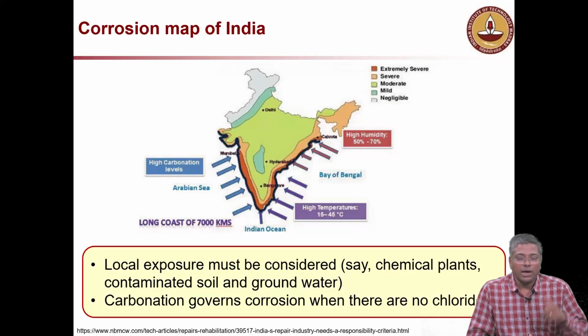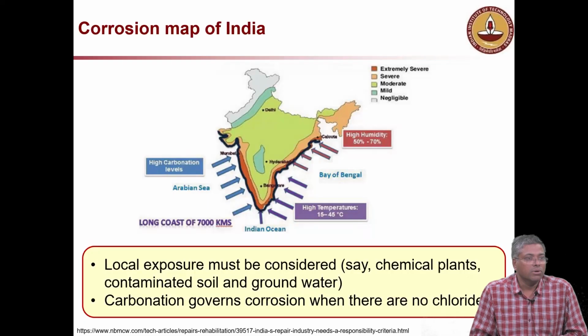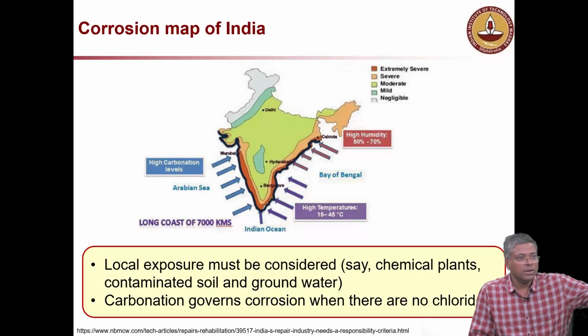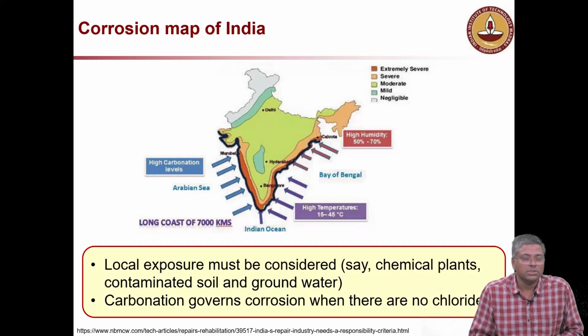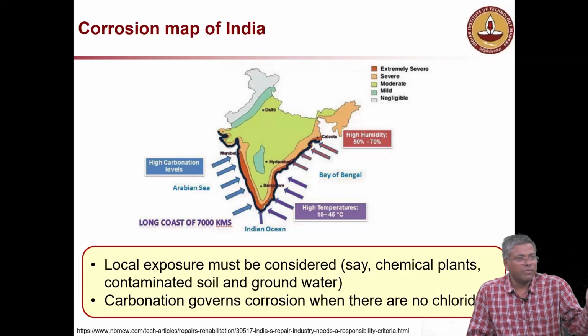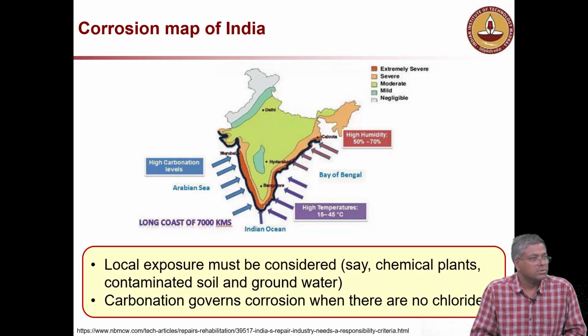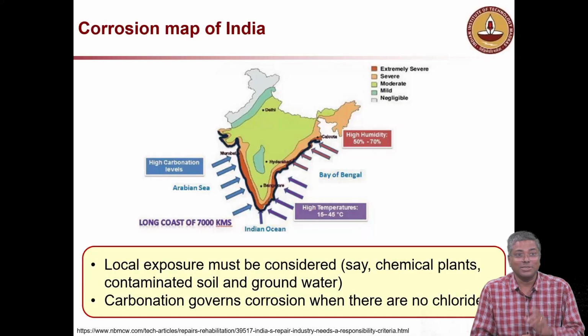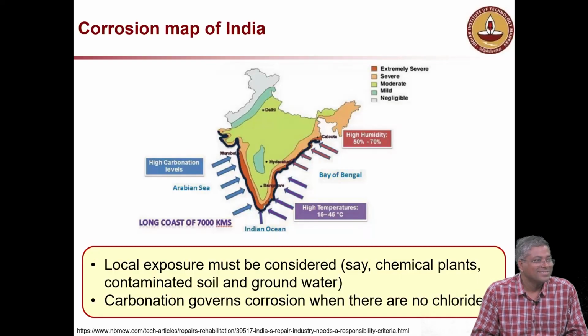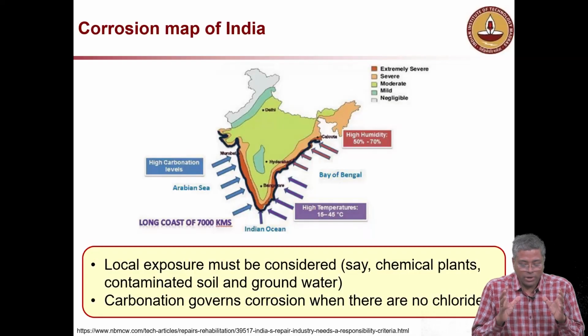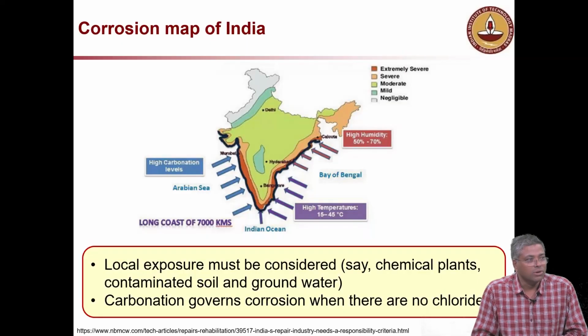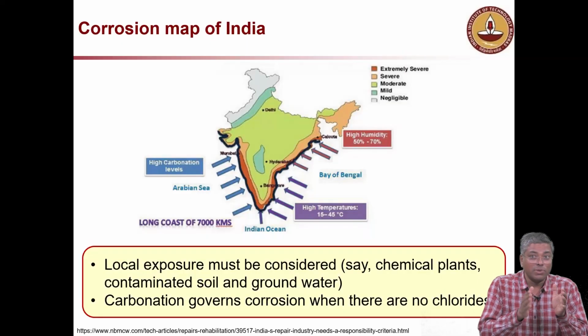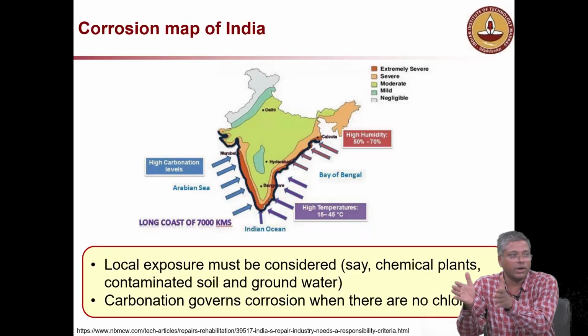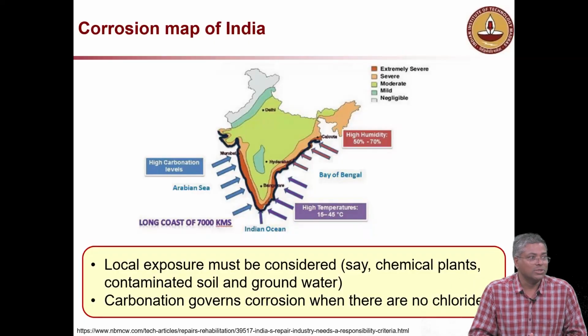Okay, I had an experience with one of the buildings in our city, Chennai, where the building is about 50 to 100 meters from the coast, and the problem was not chloride. The problem was actually carbonation. It's a silent killer. Carbonation happens when it is 60 to 70% humidity, which may be the case when you talk about 100 to 500 meters from the seashore.